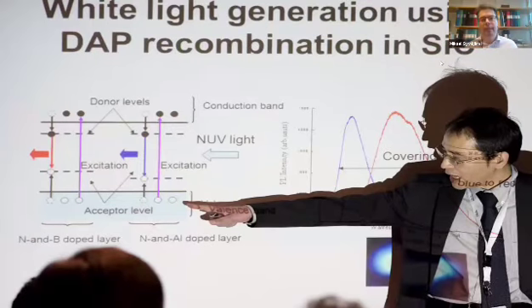And then a few years later came Satoshi Kamiyama. He proposed that let's take silicon carbide, and if we dope the material with donors and acceptors, we can get light out from silicon carbide. So silicon carbide is a light emitting material. It's not nitrides and so on. This is silicon carbide, which is the emitting material. And for that, he doesn't need pure layers. He wants to introduce certain dopants, so you get donors and acceptors for this luminescence. And then he needs thick layers, so you can have sufficient amount of luminescence from the layers.